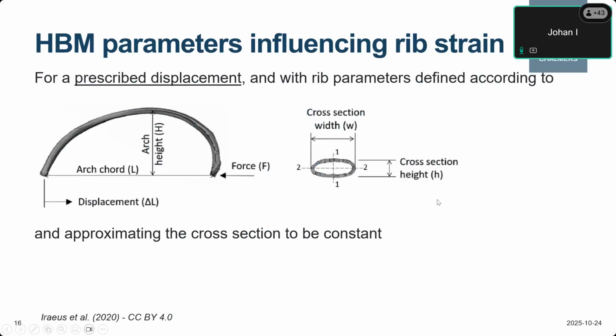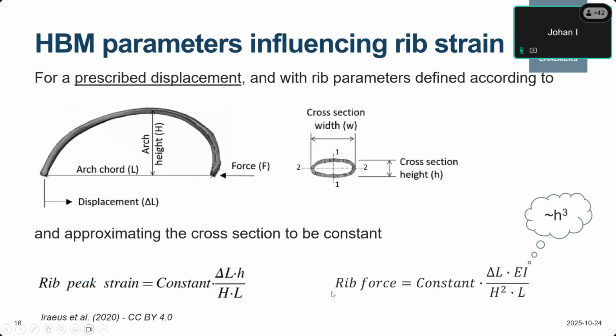just for simplicity now. Then it can be shown that the peak strain in the rib, which will be at the top of the arc, is proportional to the height of the cross-section, so this smaller dimension of the rib, and also the global shape of the rib. So we can see that we do not have any material parameters here, so for a prescribed displacement, the material doesn't matter.